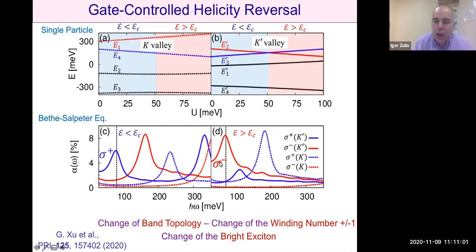In other words, on the same sample, simply by changing electric field, we are in a position to reverse helicity of the light. So the change of band topology, which leads to change of the winding number, can then be measured experimentally by looking at the changes of the bright exciton. So this is an exciting possibility because now well-established optical tools can also allow us to probe topological properties.